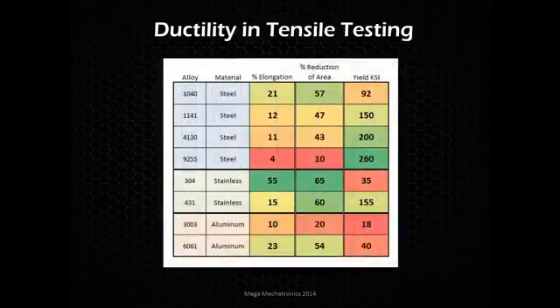So let's look at some examples of some materials and these parameters. Looking at 1141 steel, we're at 12% elongation, 47% reduction in area. 4130 steel, 11%, 43%. They're pretty close, but you can see the 4130 is quite a bit stronger. You'd probably prefer that material over the 1141 because it has similar ductility and toughness, but it is quite a bit stronger. And 9255, that's a bit harder. It is very strong, but not very ductile. And then you see the 304, 431, huge difference.